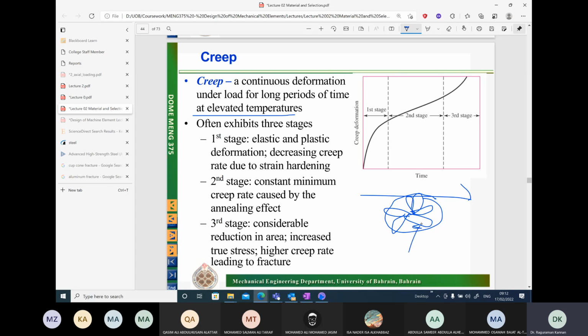These turbine blades, they are exposed to temperatures of 650 degrees centigrade over periods of time under constant loads or maybe variable loads. The loads come from hot gases flowing continuously around them, and these turbine blades will be subjected to this load at very high temperatures and for hours together. And what happens is the phenomenon of creep. Under such loads, continuous deformation takes place, and at one moment fracture will occur.